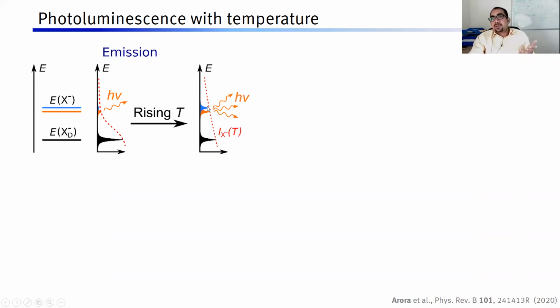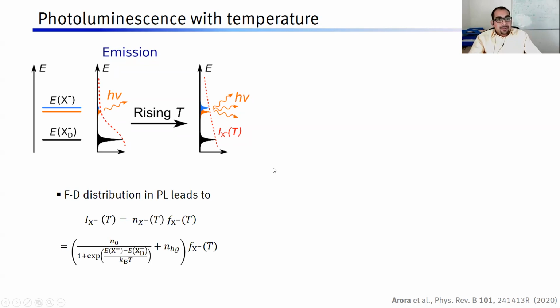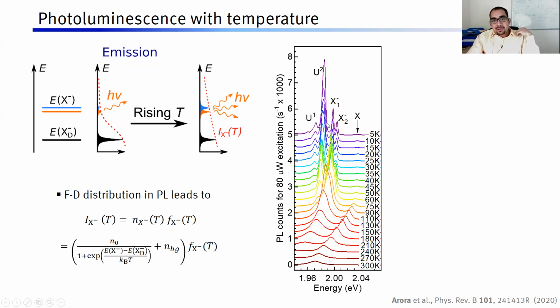Now, this is also sort of counterintuitive in semiconductors, that the emission would rise as a function of temperature, because the emission generally falls when you raise the temperature, because you increase the number of phonons, and then the two-particle processes contribute more, and so on. But let's suppose there is this Fermi-Dirac distribution of these trions. And this is what it would lead to. It would lead to an increase of light. This is what exactly happens for the photoluminescence.